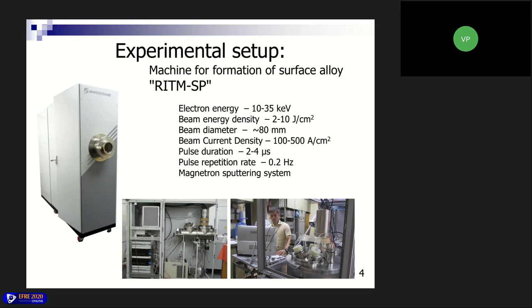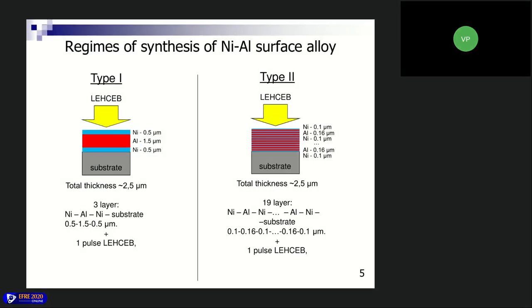The beam diameter is, as you can see, about 8 centimeters. And this machine is also equipped with a magnetron sputtering system to make metallic coatings on the substrates. So for the experiments, two types of specimens were made. The type 1 specimen, with a total coating thickness of 2.5 micrometers, consists of three layers: nickel, aluminum, and again nickel.